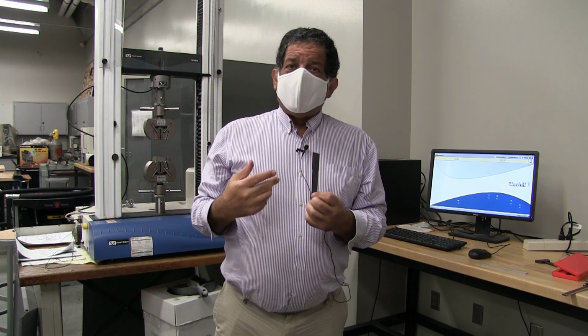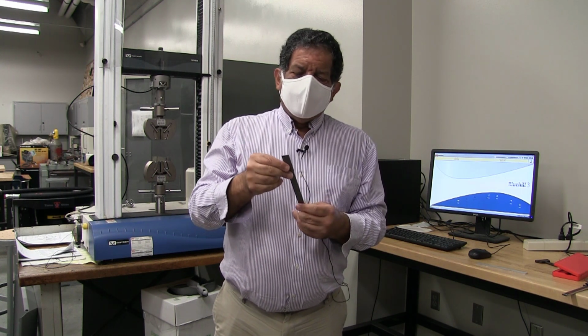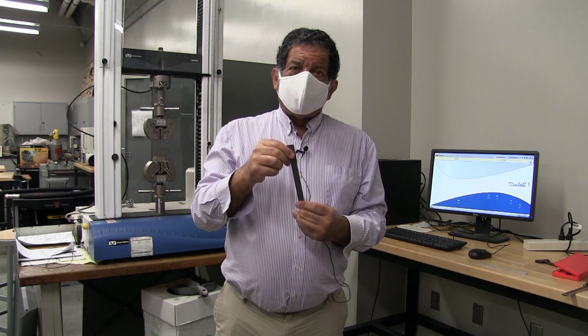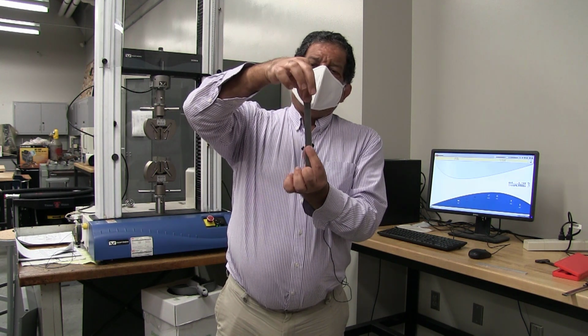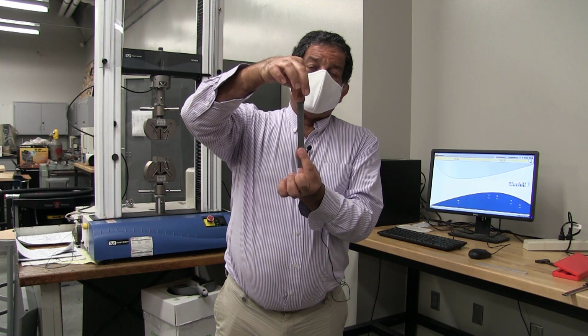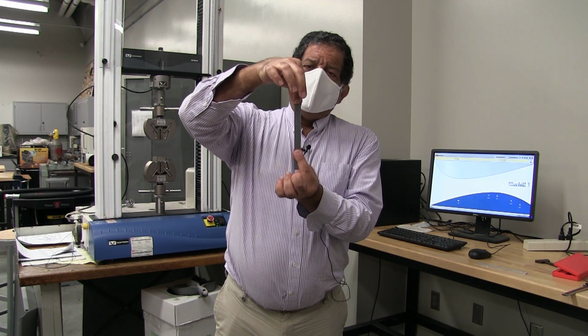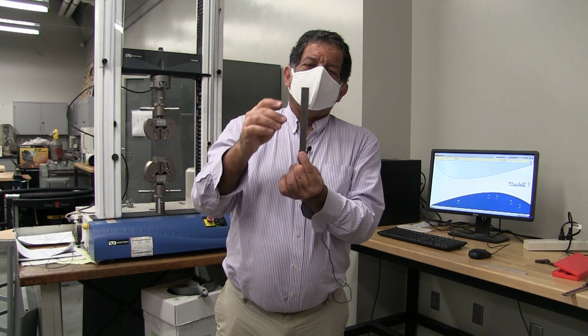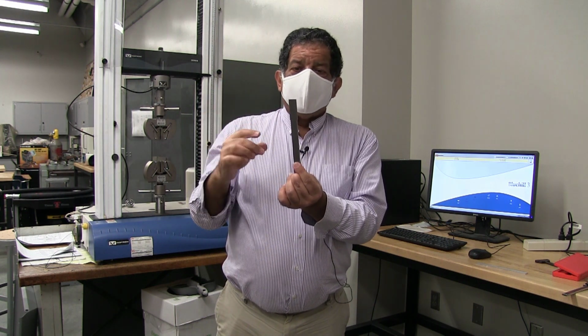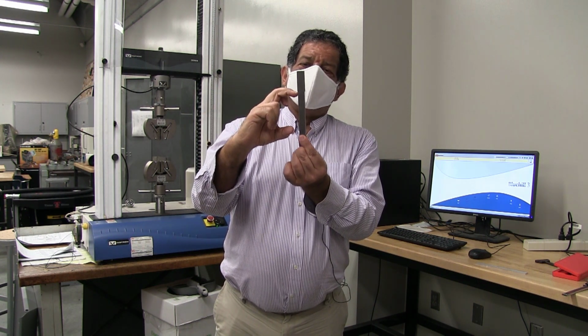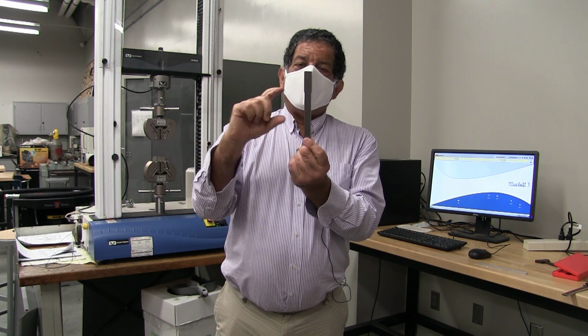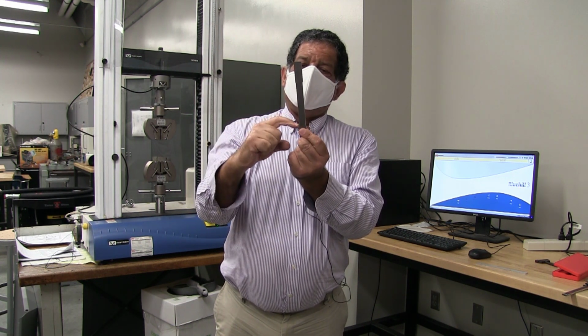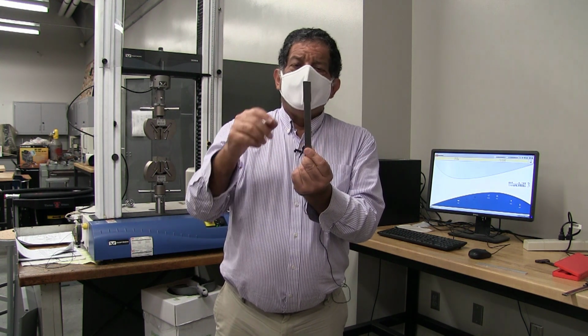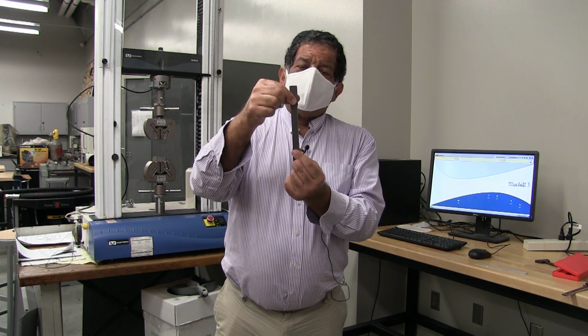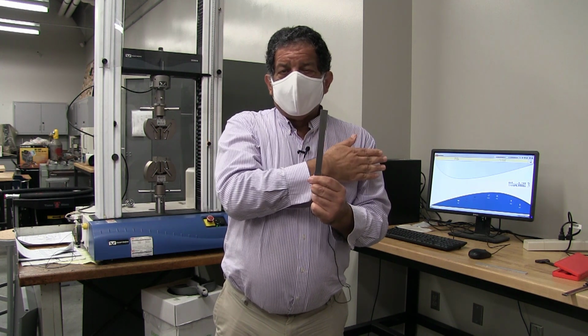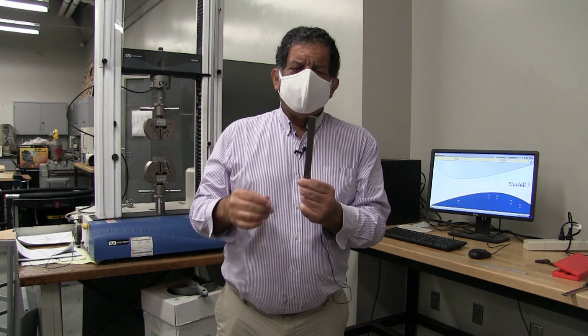The machine is going to be calculating strain in two different ways. The kind of crude calculation of strain, which it can always do, is to just measure the displacement of the ends of the specimen as it's pulling one end apart. When it calculates the strain in that way, it's going to take as the deforming length the distance between this fillet and that fillet. That's why we put that in there. And that measurement of strain is going to be used from the beginning of the deformation all the way to the end of the deformation.